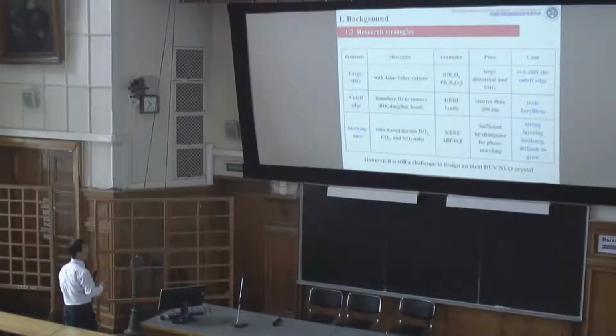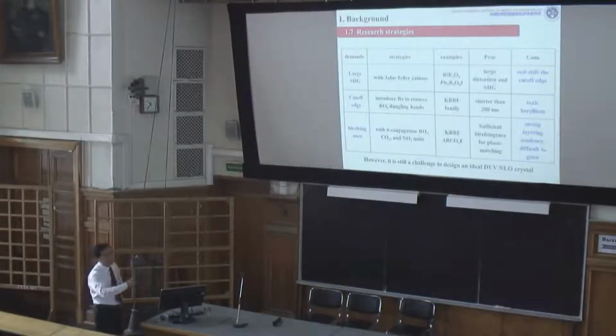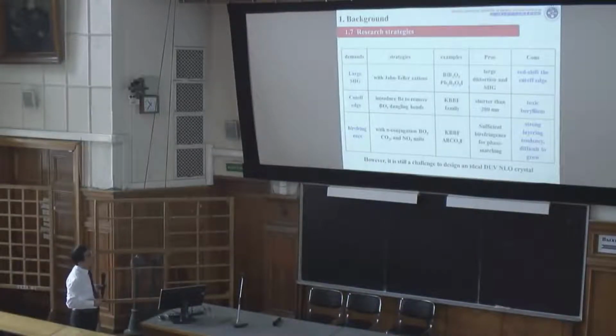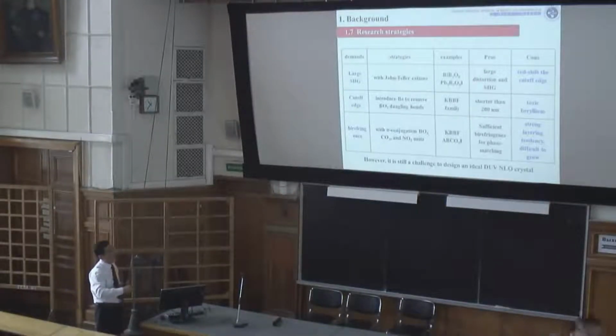And also, another group wants to introduce beryllium to remove BO3 dangling bonds because they want to make the deep UV cutoff edge blue shift. So they're successful. It means, for example, the KBBF family, this kind of material has a short cutoff edge below 200 nanometers. However, this kind of material contains toxic beryllium.